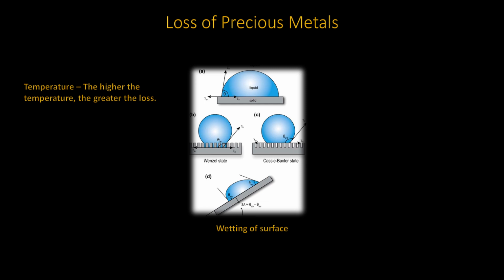Using good quality cupels and conducting a good cupellation, losses are basically due to oxidation and absorption of the oxides. Volatilization is a small percentage, somewhere between 1 and 2%. Both of these processes are directly controlled by temperature. In general, the higher the temperature, the greater the losses, especially silver.